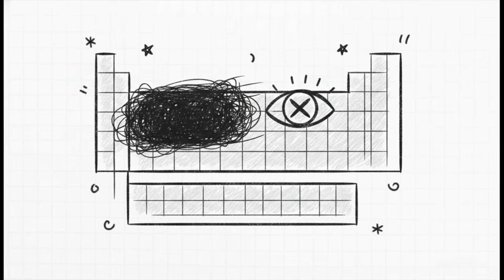Next up is what we can call the light element blind spot. If you picture the top left of the periodic table, hydrogen, helium, lithium, beryllium, and boron, these are low Z, or low atomic number elements. Well, EDS has extremely poor sensitivity for these. They are incredibly hard to detect. If your nanomaterial's whole function relies heavily on the presence of lithium, for example, like if you're doing cutting-edge battery research, EDS is really going to struggle to give you the clear chemical picture you need.